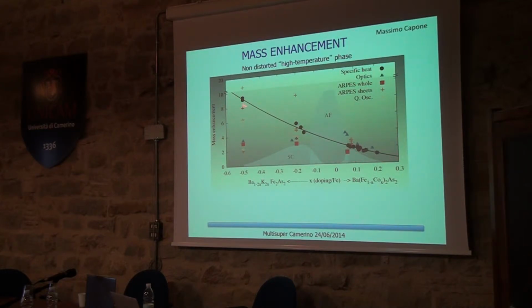So the black dots here, which I joined with a black line, are from specific heat. And you clearly see that this doesn't care so much about what happens around the parent compound, but increases all the way down to here. So when I decrease the number of electrons, going from 6 to something less. Then the blue line is what is estimated from optical measurements. And you see that the values are much smaller, but still you see a slight upturn.